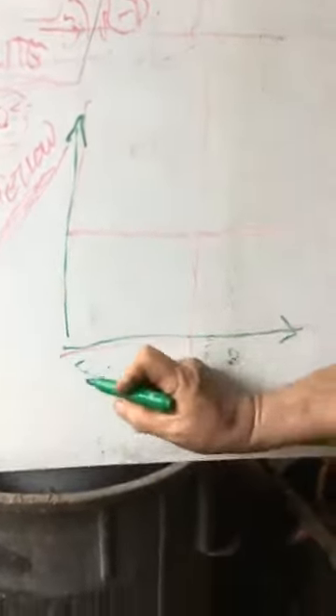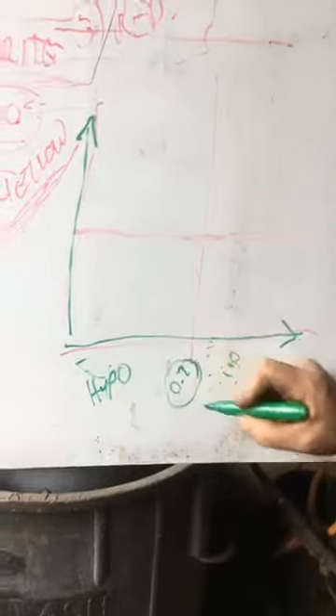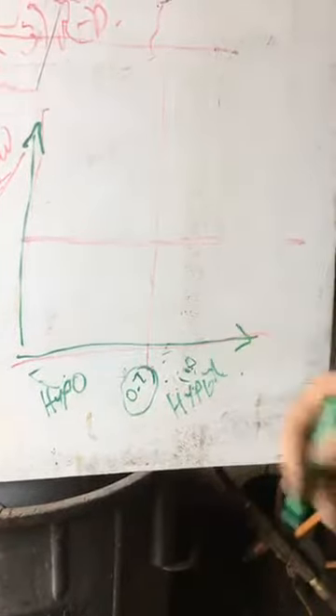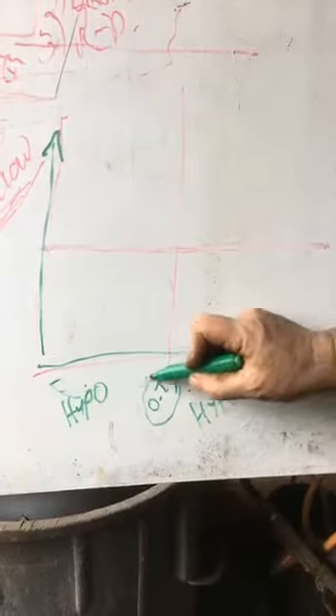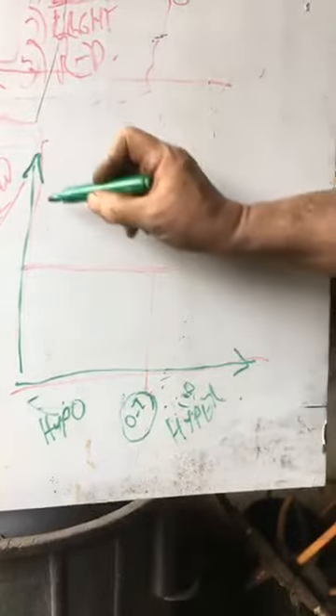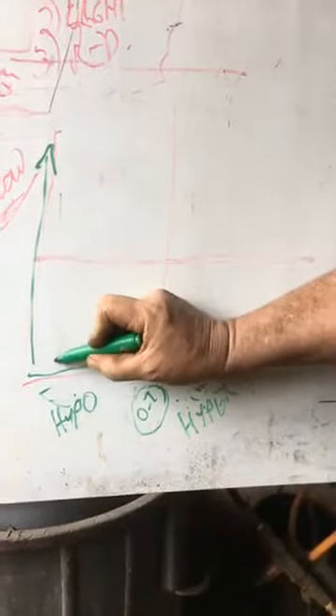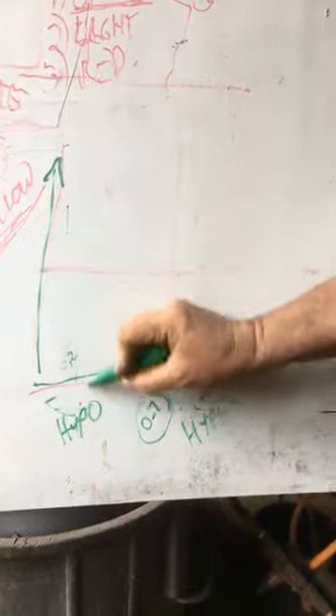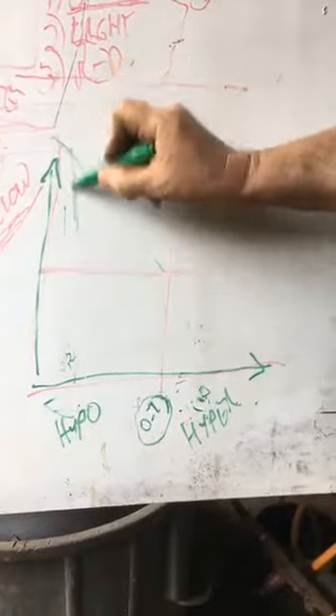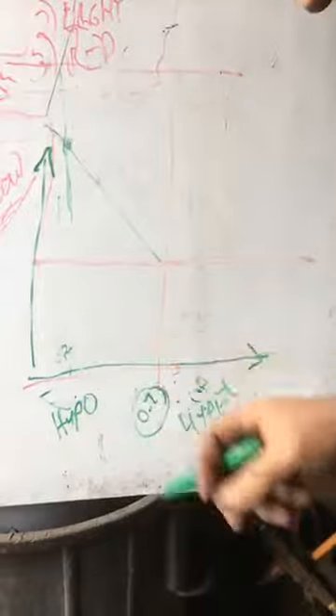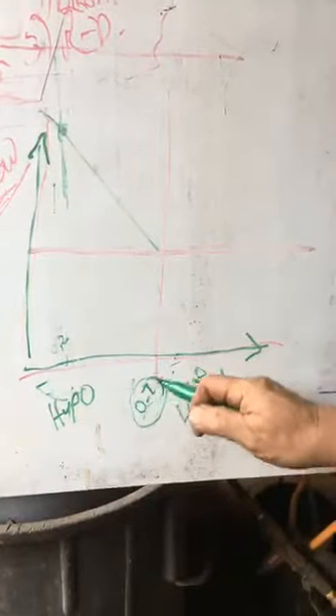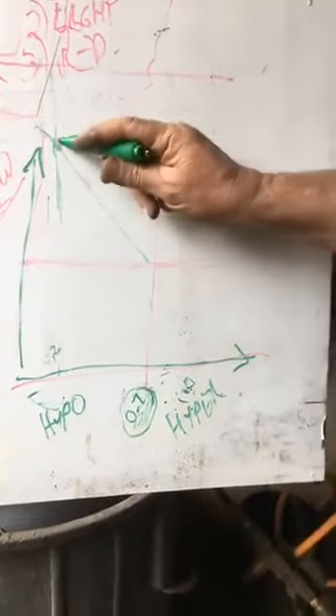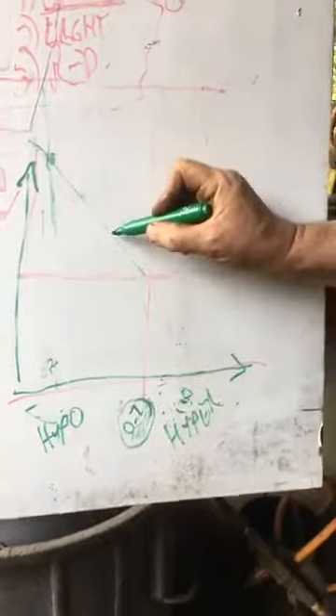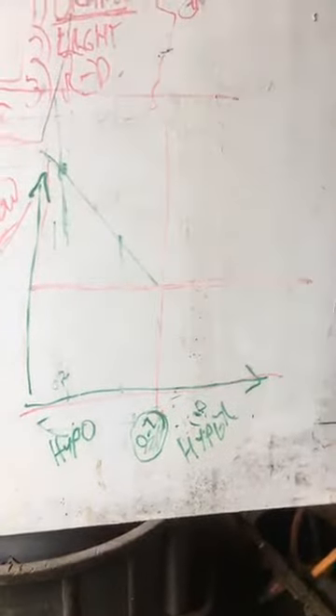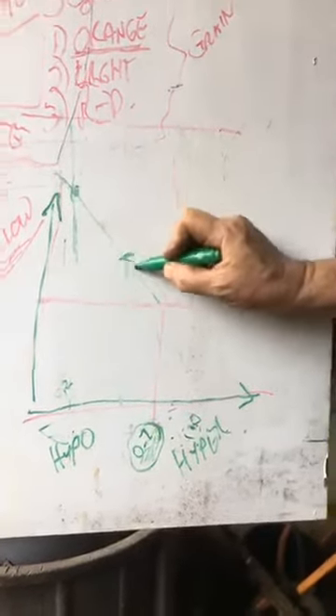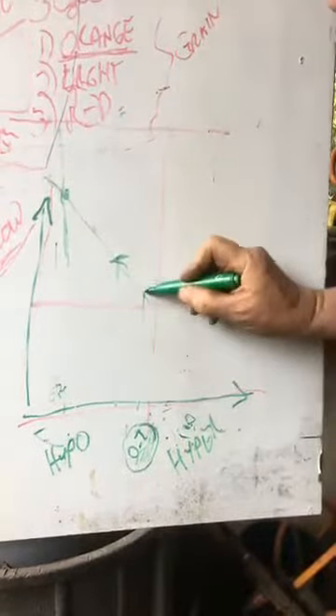So these are hypoeutectoid steels, and these are hypereutectoid. Not that you really need to know this, you just need to be aware of it. So 0.7% is a golden medium. So your mild steels are about 1020, 0.2% carbon, and that's at about there. So you can harden mild steel, but it will be at a higher temperature. So that 0.2% carbon is going to fully saturate whatever ferrite's there, but it's not enough to make it a good working edge. So you have to get it hotter before you harden it. So EN45, 0.45% carbon sits there. So those guys who want to work with EN45, you have to heat it up hotter than 5160 down there.